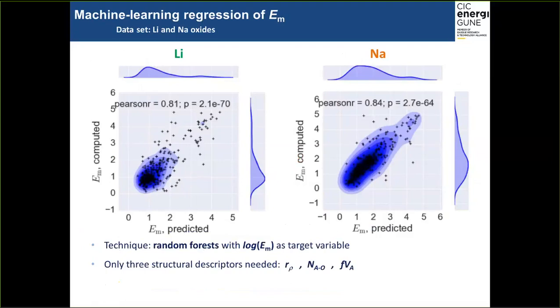So we found that reasonably good predictions can be obtained by using only the following three descriptors: the percolation radius, the cation volume fraction, and the cation-anion coordination numbers. The inclusion of more descriptors does not improve the predictions.